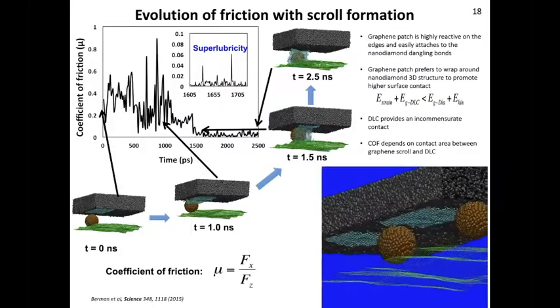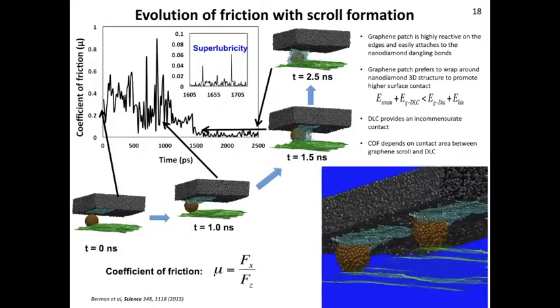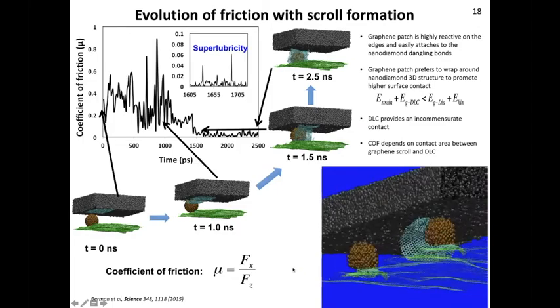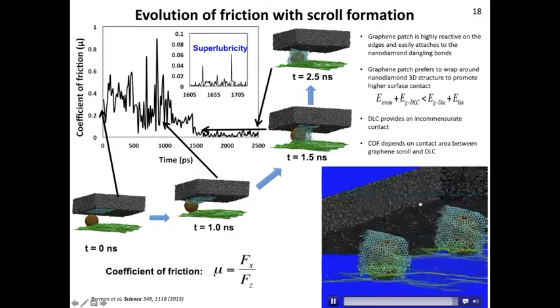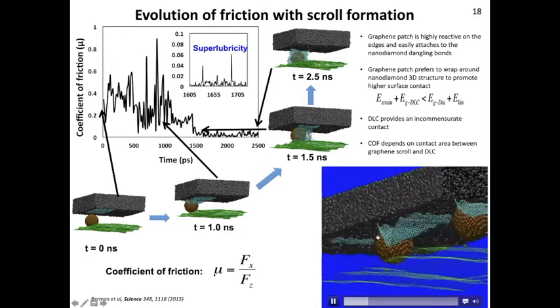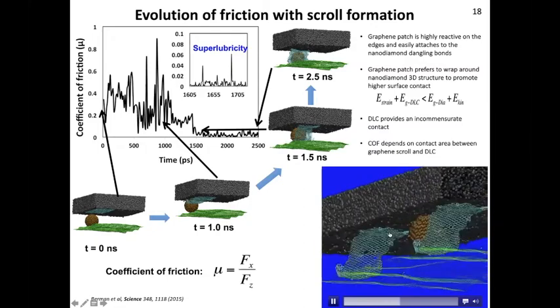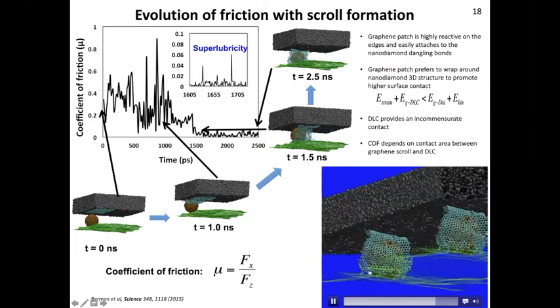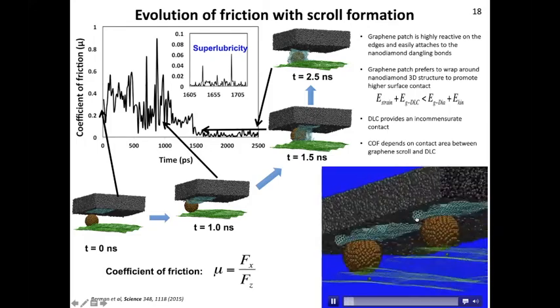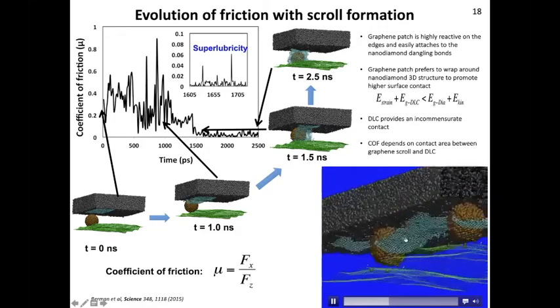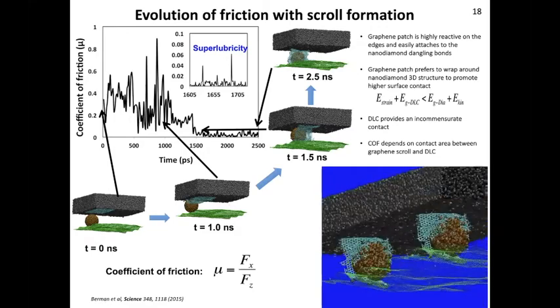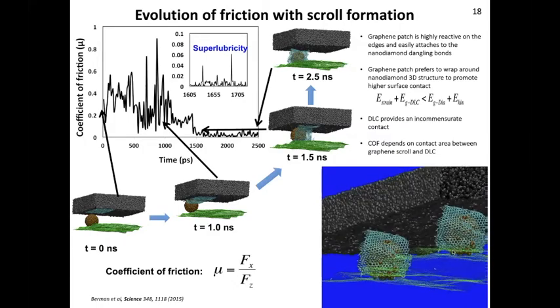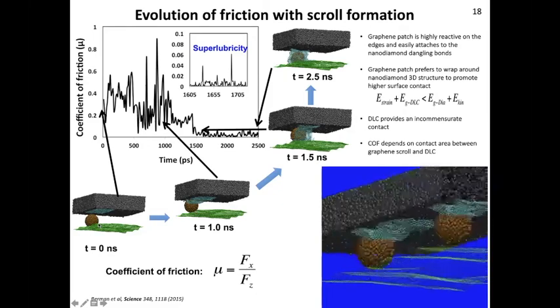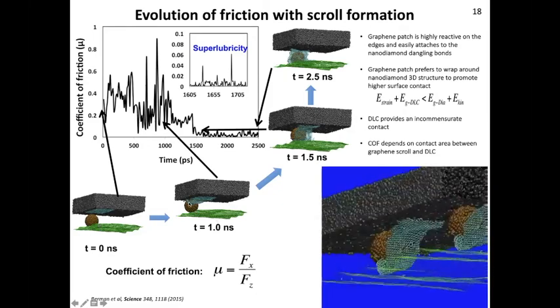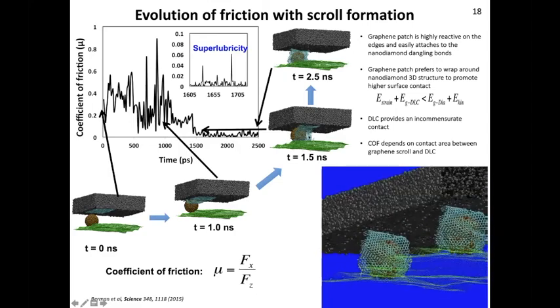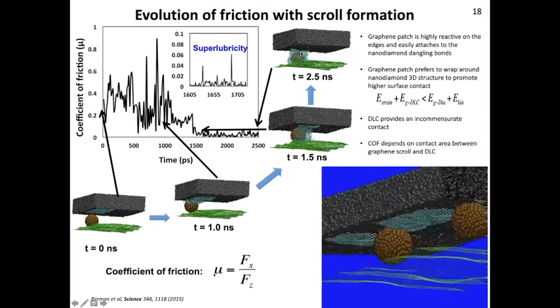To look at this, we ran some molecular dynamics simulations, and I hope the video shows you what is happening. It will be running now again. This was our initial configuration: we have these graphene flakes and we have diamond particles. During the sliding, due to the dangling bonds on the diamond surface as well as on the edges of the graphene flakes, we have an initial bonding and attachment of the graphene edges to the diamond particle. At 0 nanoseconds we had just a patch, then it starts to attach to the diamond, and then it actually wraps around the diamond nanoparticle.